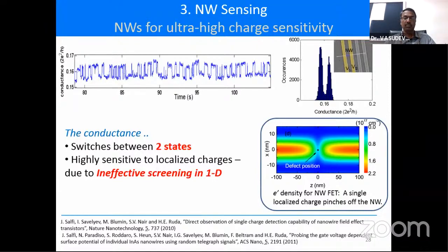And looking on the left, you see a trace of conductance fluctuations, random telegraph noise. What you can see is that the conductance is fluctuating between apparently two states, a lower state and an upper state instantaneously. And to prove to you those are two well-defined discrete states, if you look back to the figure on the right, which shows conductance and the number of occurrences, that's a plot where for each conductance level shown on the left-hand axis of the other plot, we count up how many occurrences there are, and we do that all the way across the diagram.